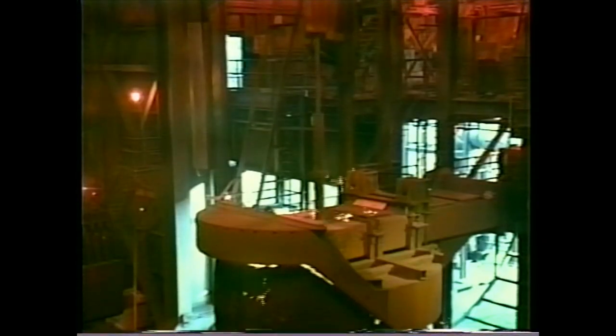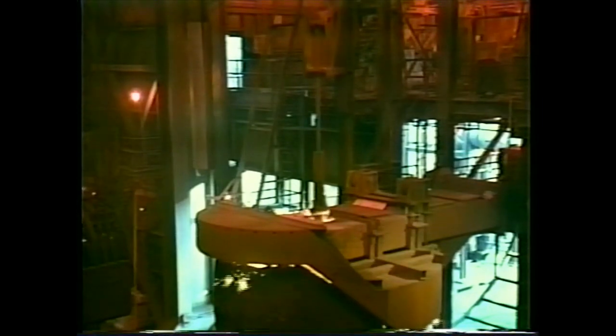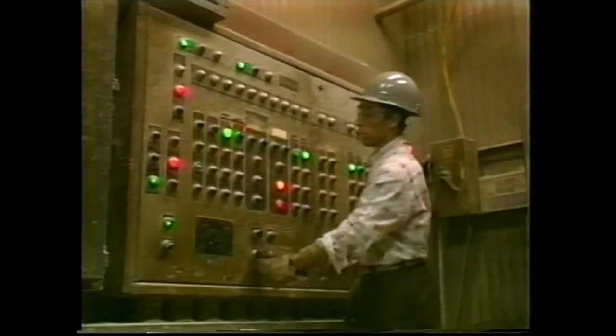At the same time, the hot metal man directs the charging crane operator to move the ladle of hot metal from the hot metal hole. The ladle is moved to the desulfurizer, the skimmer, or the furnace, depending on the sample analysis and the grade of steel to be made. The desulfurizer operator removes the sulfur from the hot metal and skims the resulting slag before the metal is charged into the furnace. The track hopper man makes sure the flux bins are full with the correct fluxes. Fluxes are added to the heat to remove the impurities.